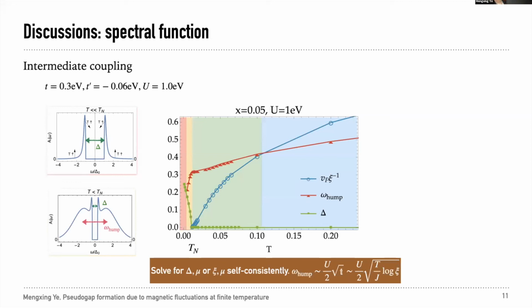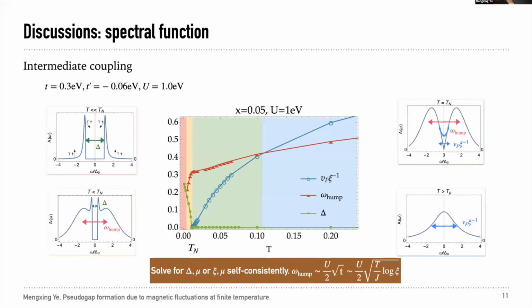Around the Néel temperature, in this green region, we see that the SDW gap vanishes, but this hump energy remains relatively constant. It disappears only when the fermion energy becomes larger than the hump energy, in this blue shaded region, and we will see the Fermi liquid-like behavior.